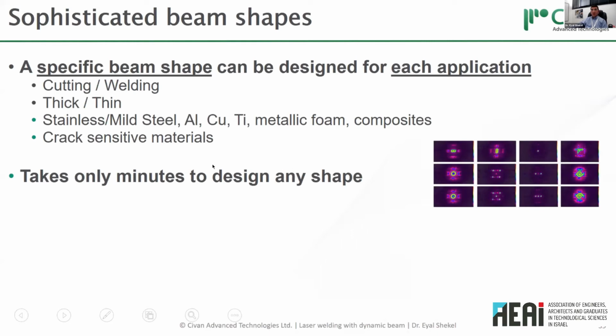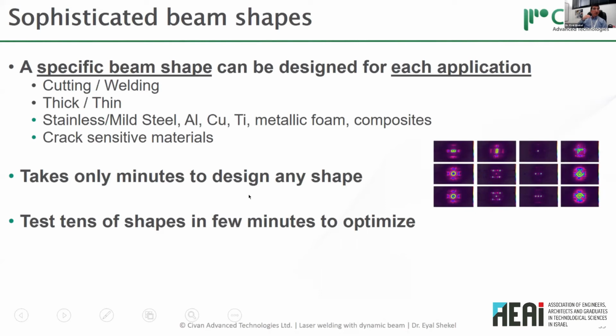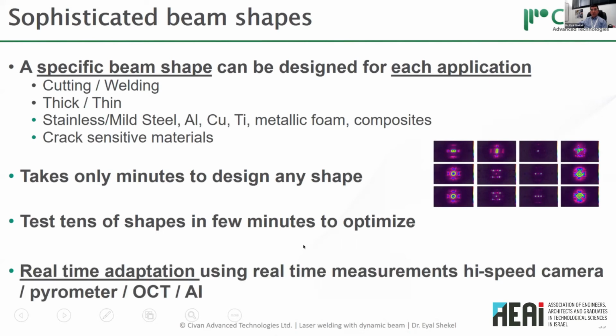But as you saw, it only takes minutes to design any beam shape, and you can optimize the beam shape, and it takes minutes afterwards to upload any beam shape into the laser and actually optimize to get the optimal process. In the future, we think that we will also be able to do real-time adaptation, because we can change the beam shape, like I mentioned, in nanoseconds. So if you have some high-speed camera or pyrometer or OCT, you can actually, during the process, optimize the beam shape to get the best possible process.